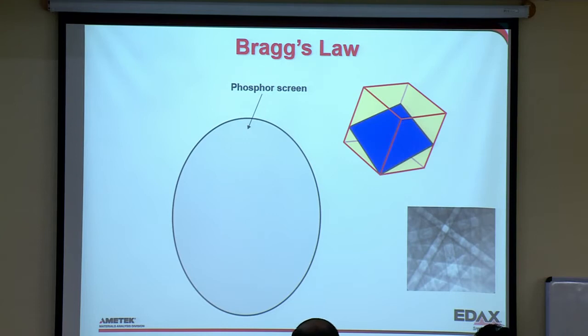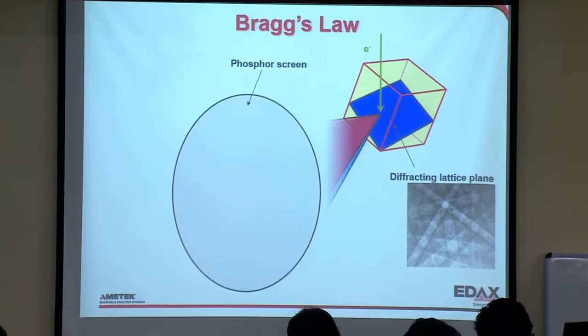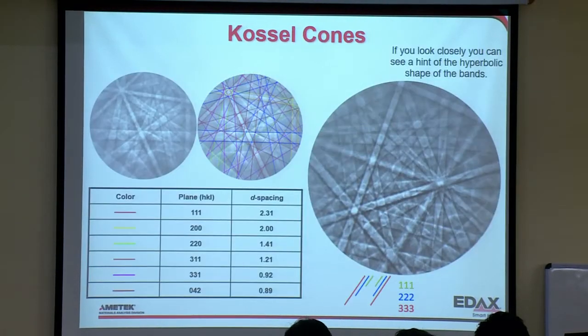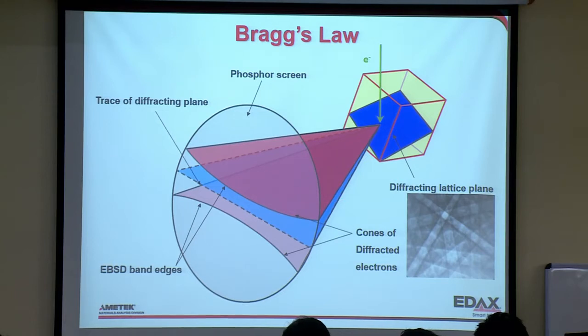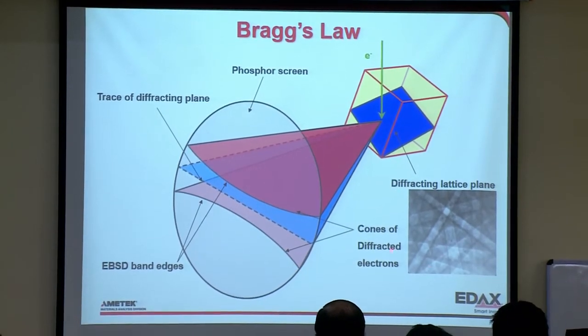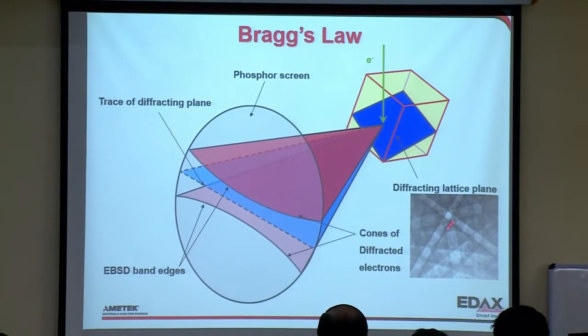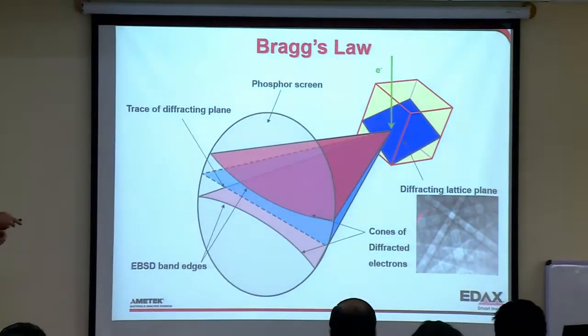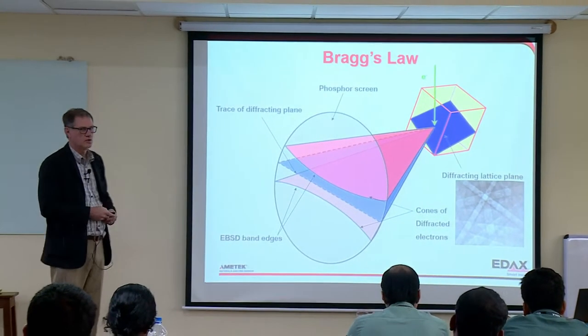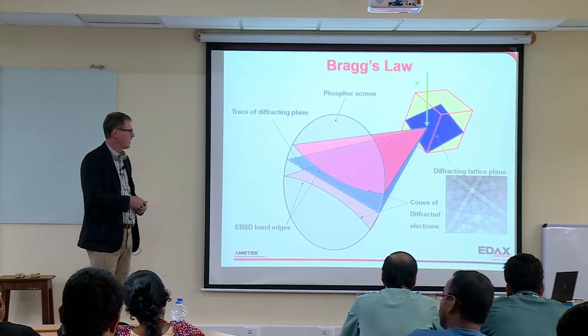So if you think about it this way, we have an electron coming in from some direction. It interacts with the plane, and it produces these cones of diffraction, sometimes called Kossel cones. And you end up with a pattern. If you put a phosphor screen in here, you end up with a pattern that looks like this. When electrons hit the phosphor screen, they luminesce the screen, and you basically are converting electrons to light. And from that, you can detect this with film or with a camera, and you can get a pattern. So the planes in the pattern reflect these curved lines. And you'll see you don't see the curvature, but it is there. I'll show you an example later. But these bands here correlate to planes in the crystal structure, in the crystal lattice.